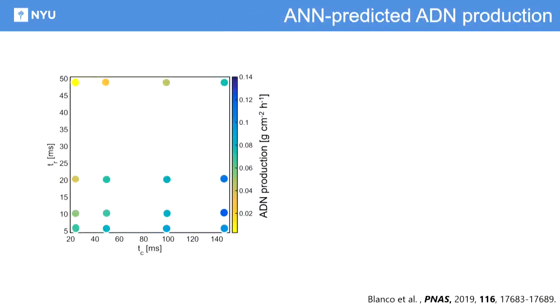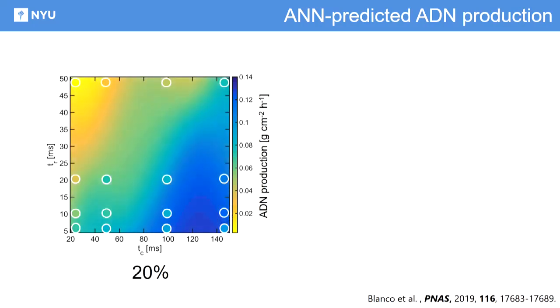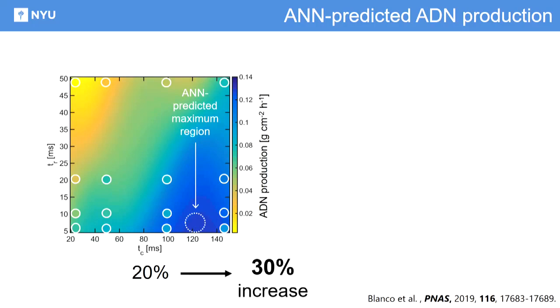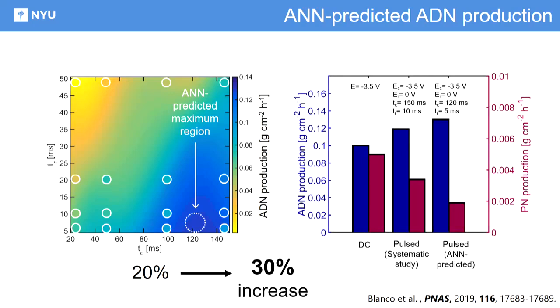So if you put all the data that we had collected in terms of the cathodic time, resting times, and production rate of adiponitrile, here's your point of 20% increase of production rate. We can fill the rest of the space using these predictive tools, which showed us regions in which we can actually enhance the production rate of adiponitrile. So Anila went back to the lab, ran the experiment, and then we actually further enhanced the production rate from 20% to 30% increase. And we do that by further enhancing selectivity. We lower the production rate of propionitrile as we increase the production rate of adiponitrile.